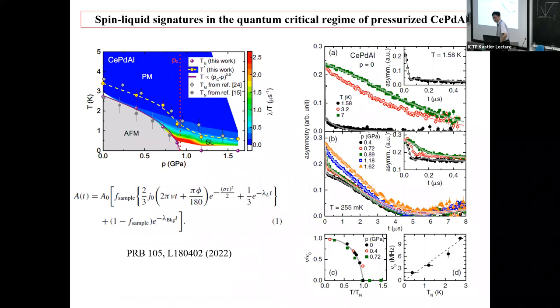Okay, and more recently, just this year, there's a MuSR experiment on this material, this undoped one, which indicates indeed this is a spin liquid type, because the MuSR signal shows exponential decay of the spectra with some oscillations if this state is in a long range order phase. But above the critical pressure in this spin liquid region, the MuSR doesn't pick up the oscillation. So there's no oscillations, meaning no long range order. And it is indeed a signature of a paramagnetic spin liquid phase. Okay, so this phase is real.